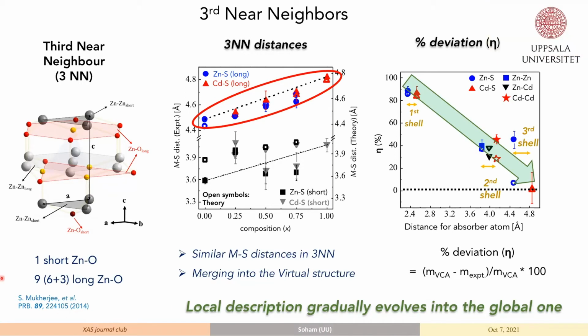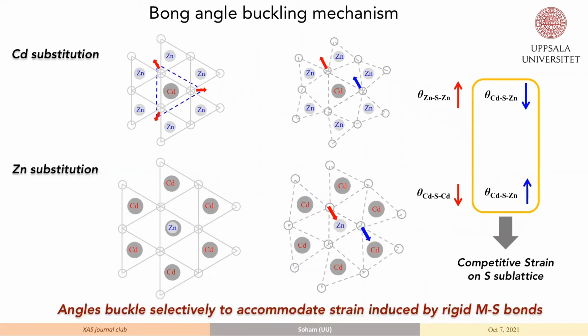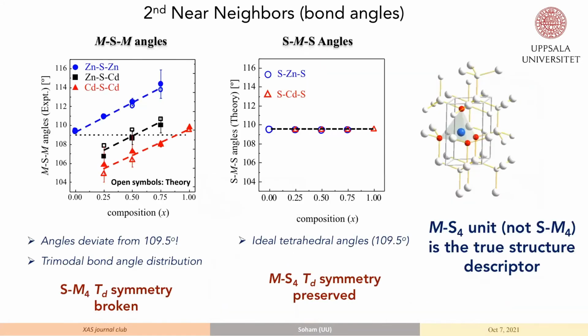Yeah, so I think it was two slides previously, you were describing metal, sulfur, metal bond angles. Yeah, here. If you did this, keeping the cation the same and doing this as an anionic solid solution, would you use the opposite model to describe the changes? Exactly. Because what turns out is that this is related to the sublattice that you're doping into, and not related to the choice of the metal or the ligand. It depends on the sublattice. So the definition will just be reversed. There, the metal-sulfur-4 symmetry will be broken, and the ligand-to-metal description will be preserved. Thank you.